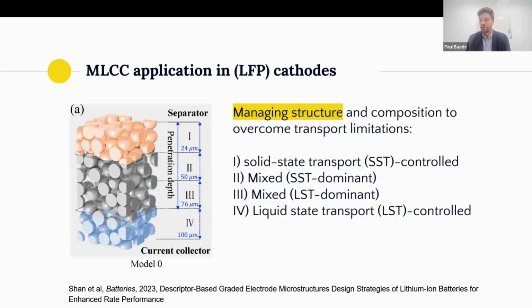You can make the same argument for graphite anodes for fast charging applications, but ultimately the value mechanism is about overcoming transport limitations. Now, what kind of transport am I talking about? It's solid-state transport, so ionic transport within your active material particles, but also liquid-state transport in the electrolyte. So when you talk about C rates of 1C, 2C, or even 5C at those thicknesses, you run into significant capacity loss during your cycles.